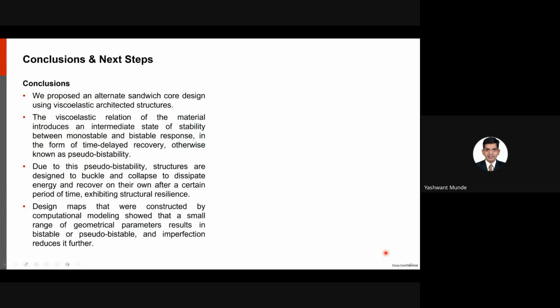So this comes to the end of my first part of this talk. That is, we proposed an alternate sandwich core design using viscoelastic architected structures. The viscoelastic relaxation of the material introduces an intermediate state of stability between monostable and bistable in the form of a time-delayed recovery, otherwise known as pseudo-bistability. And due to this pseudo-bistability, structures are designed to buckle and collapse to dissipate energy and recover on their own after a certain period of time, exhibiting structural resilience.